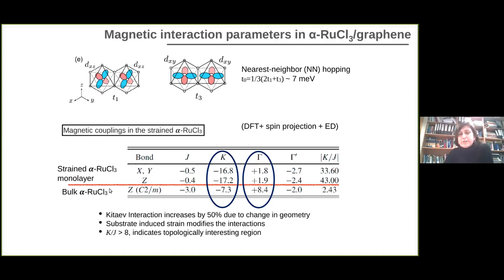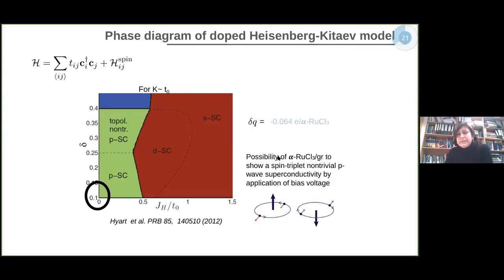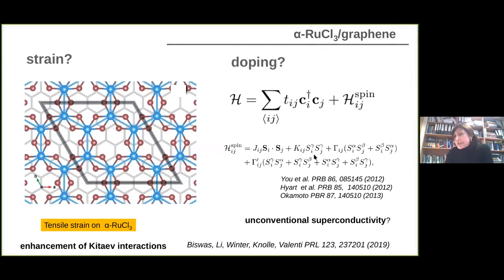And here I'm showing the results. This would be bulk alpha ruthenium trichloride, which has an important Kitaev interaction, but also an important gamma interaction. By straining the system in the construction of the heterostructure, the Kitaev interaction gets more dominant, and the gamma interaction is reduced. So, in other words, this heterostructure is going in the direction of having ruthenium trichloride described by an almost pure Kitaev model, without other interaction terms. And there have been a few studies considering now the doping, because as we were discussing, there is doping in the ruthenium trichloride, even if the itinerancy is small.